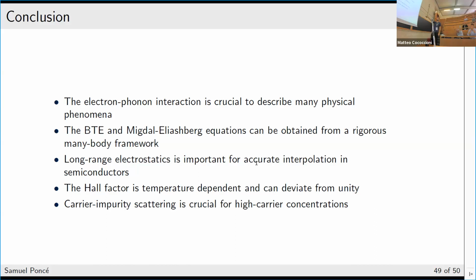In general, the long-range electrostatic is important, not really for the superconductor because you are dealing with metals in which you don't have long-range electrostatic, but for semiconductors, insulators, slightly doped semiconductors, then it's important to describe the long-range electrostatic accurately if you want to do accurate interpolation. In general, the Hall factor is temperature dependent and can deviate from unity, so it's important to always account for it. And here we've also shown that the carrier-impurity scattering is important whenever you have some significant doping of the material. Okay, thank you.